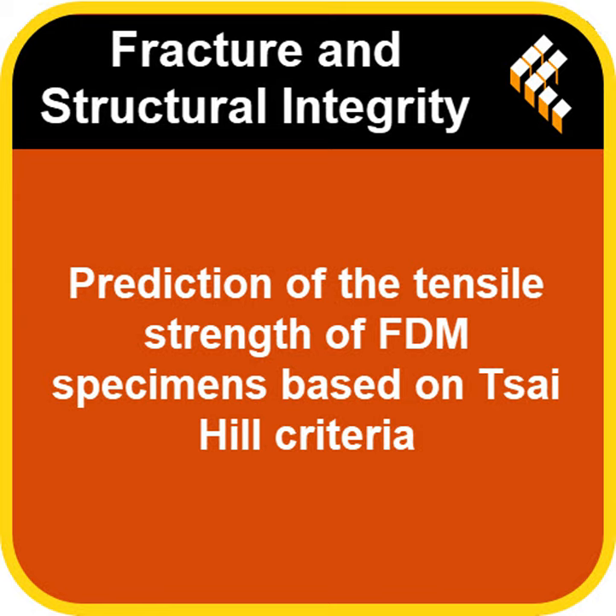Even better. For the 45-degree parts without the contour, the model predicted 48.9 megapascals. The experimental measurement, 48.62 megapascals. That's an error of just 0.6%. Extremely close. That's almost dead on. So why was it slightly less accurate for the parts with the contour?